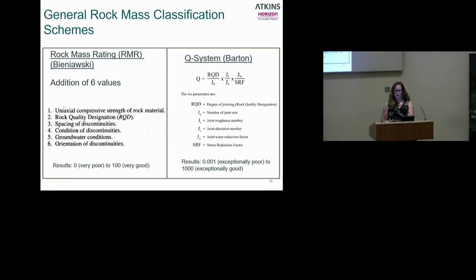Although we could have used these, we felt as though 3 or maybe 4 of those parameters we didn't have a very good hold of on site at that time, partly because the client and the designers hadn't finished the design. They didn't necessarily know what depth or loadings they were going to have in the buildings. We also had to use previous site investigation data, so we couldn't then ask anyone to come and record extra data that we could for the detailed onshore investigation.